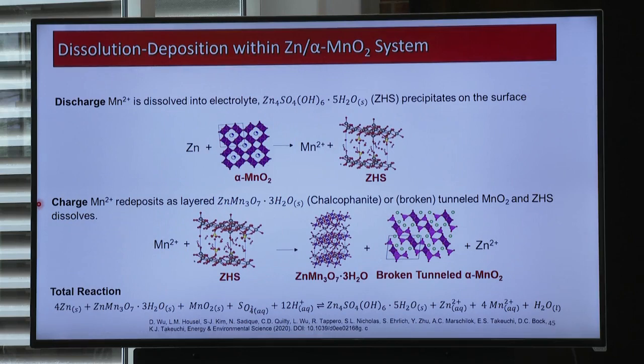We start with zinc alpha manganese oxide. Upon reduction, we form manganese plus 2 that dissolves in the electrolyte. In this case, we're forming zinc hydroxysulfate. This is a precipitation, so this also tells us that there has to be associated proton insertion into the manganese oxide to precipitate ZHS. On charge, the manganese 2 is oxidized, and as the pH becomes more acidic, the ZHS dissolves, and we end up with two things. We end up with a layered zinc manganese oxide as a charge product, as well as an alpha manganese oxide. But in this case, it no longer has intact tunnels.